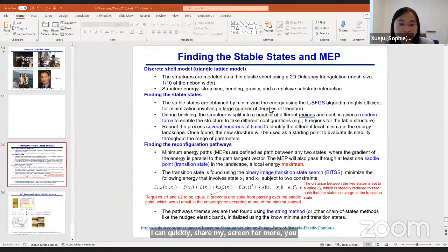So basically this is what we did. We use a discrete shell model to model the structure and minimize the structure energy. Regarding finding the stable states, we used this algorithm, which is very efficient for minimization involving a large number of degrees of freedom. For the bulk of the structure, we split it into a number of different regions and give a random force to enable the structure to take different configurations.